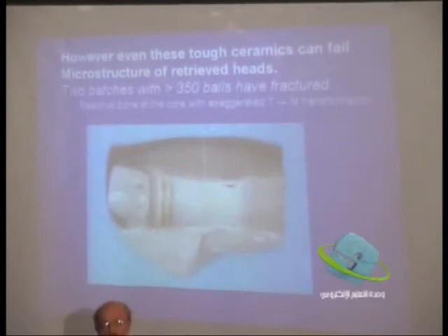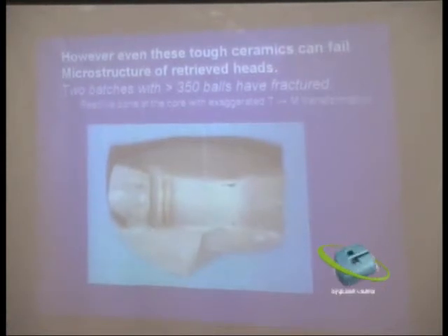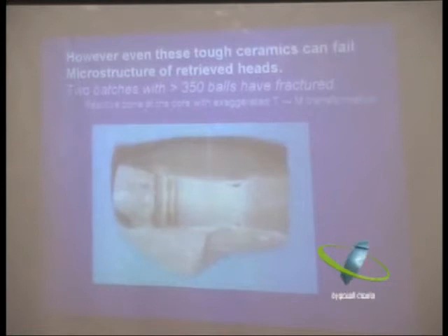Now, there is a problem with zirconia. This problem has occurred in the orthopedic industry, and it almost killed the use of zirconia for orthopedic applications. 350 hip balls made of yttria zirconia, exactly the same as you're going to use with patients. And they all fractured. This was in 1 or 2 batches of material. These failed. And this happened about 7 or 8 years ago.